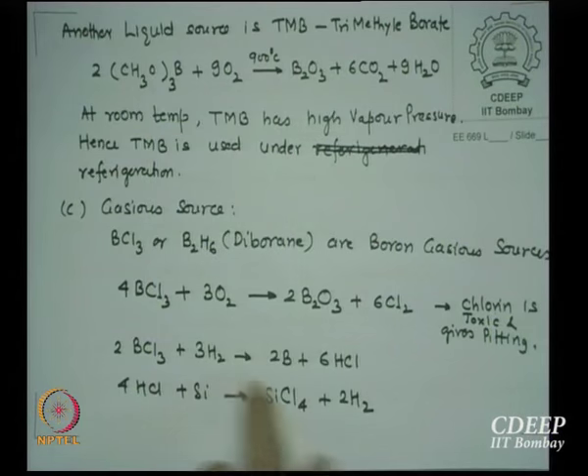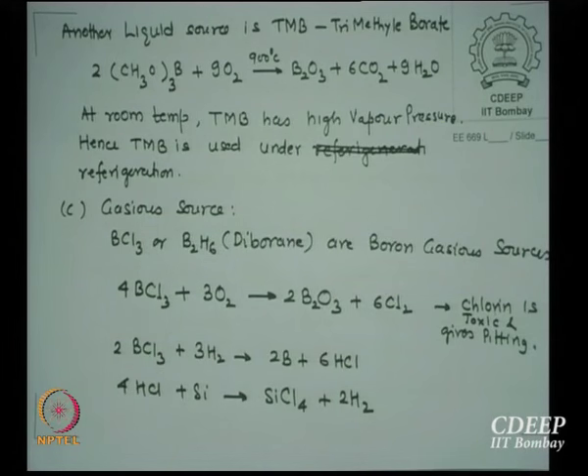BCl3 plus 3H2 is 2 boron plus 6HCl, and here is that issue. If there is an HCl, there is a pitting. 4HCl plus Si, this is what it means, silicon chloride will form. So some spots this may go, okay. If it is hydrogen free, absolutely no issue.